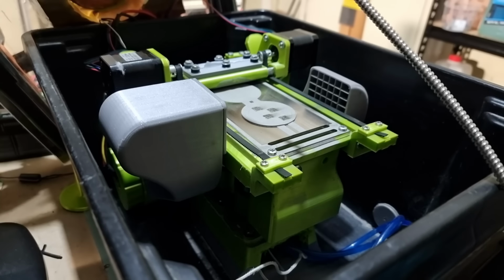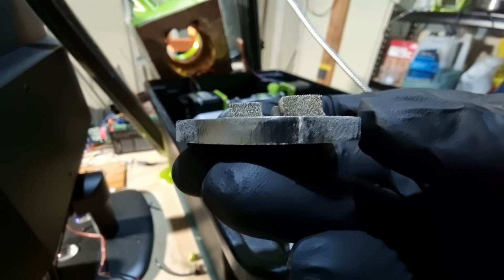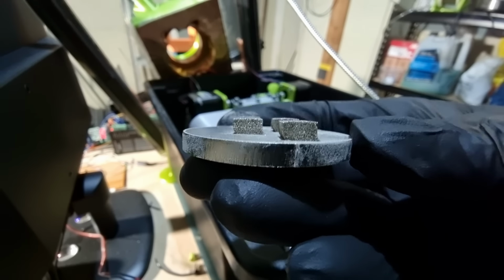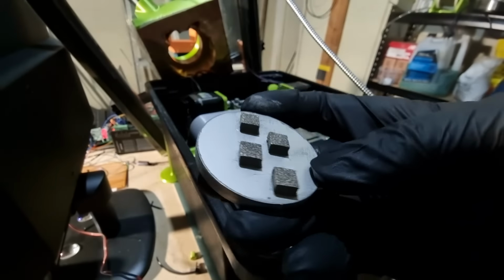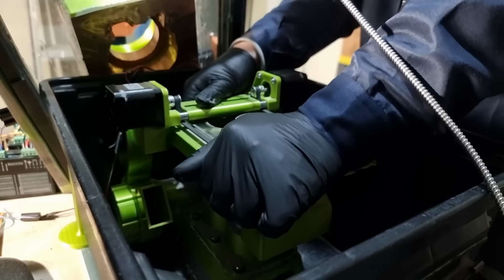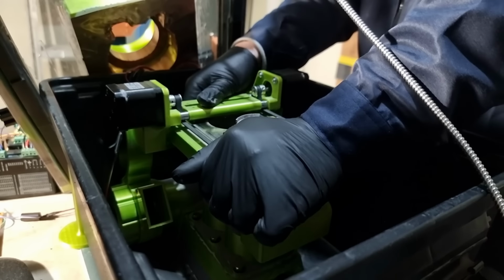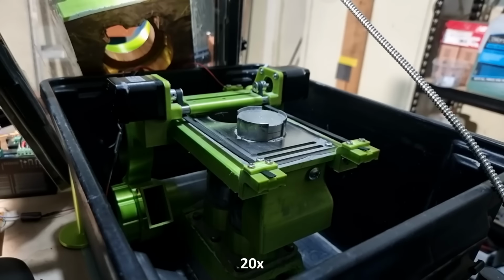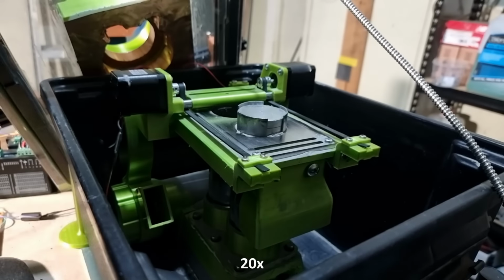Again, another series of tests, but this time at much more conservative speeds. These would result in stunted cubes after running short on powder. They did yield much better strength, but as you can see they are rather crooked due to the powder bed failing. I had to stop and address this before going any further, as this was no doubt impacting the focus of the laser, along with the geometry of the test prints.